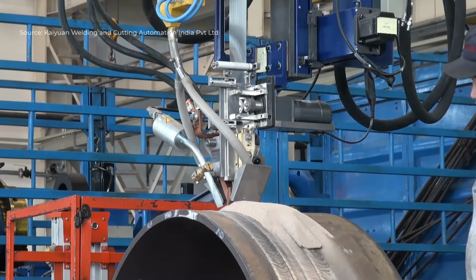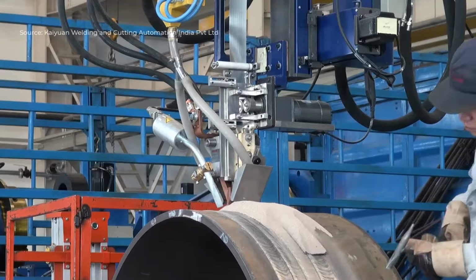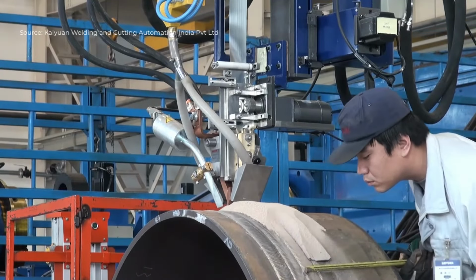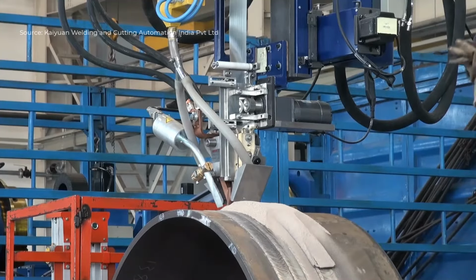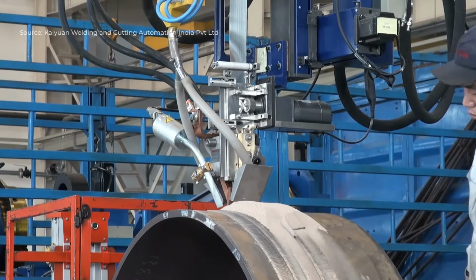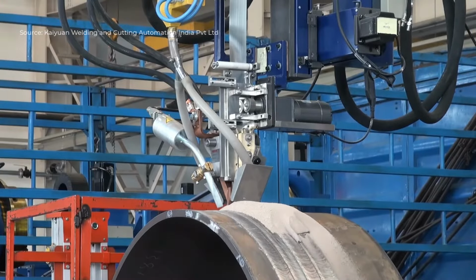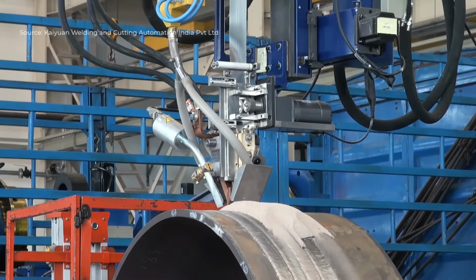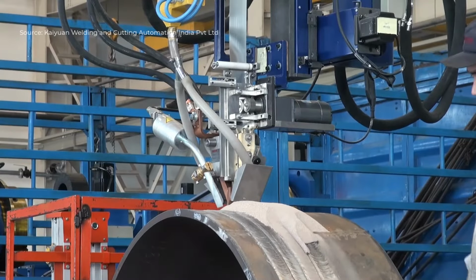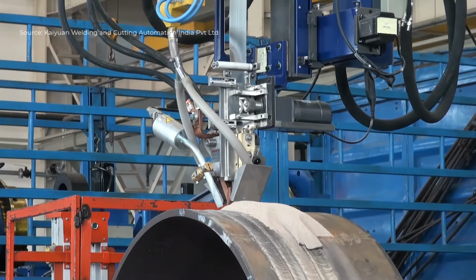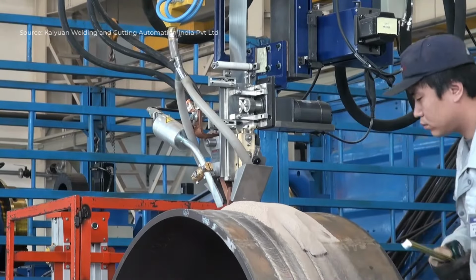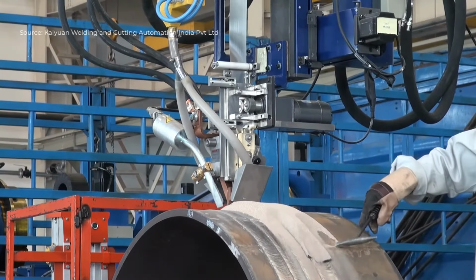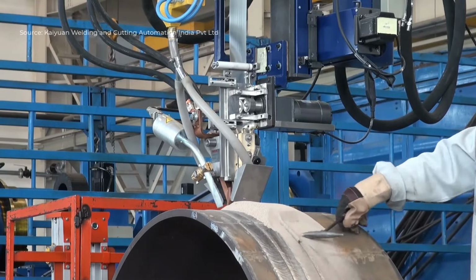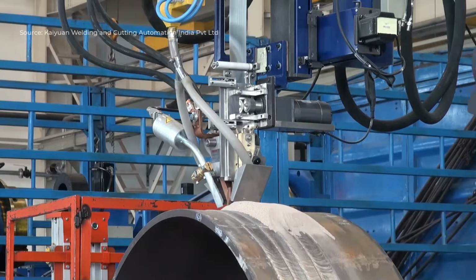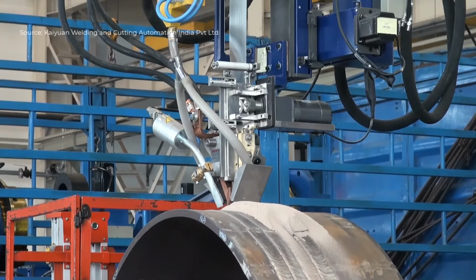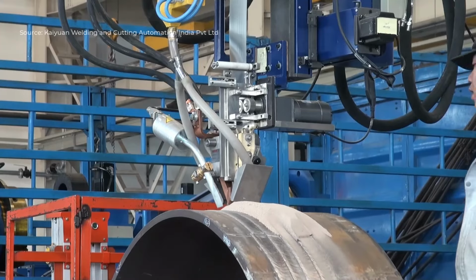In submerged arc welding, a strip electrode is continuously fed under a layer of flux, where the arc melts the strip and base metal to form a corrosion-resistant layer. In electro slag cladding, the strip is melted by the heat of molten slag instead of an arc, allowing for thicker deposits and higher efficiency. Both methods ensure strong bonding, uniform coating thickness, and excellent metallurgical quality, providing durable protection for the pressure vessel's inner surfaces against corrosion and high-temperature conditions.